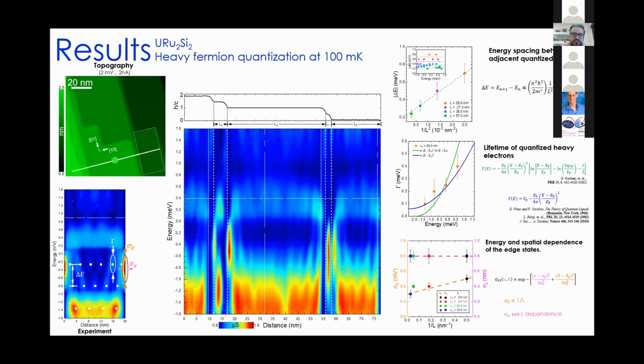With this analysis, we also did an analysis on all the surfaces. For example, here we analyze this conductance line that I put here as a white line. Here you can see the profile across the topography, and as you can see, we have different terraces with different widths. So we did the same analysis that I explained for this terrace for the other terraces that we have here, for this smaller one, and this tiny one that we get here.